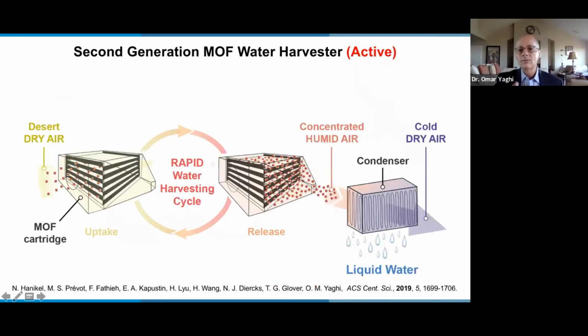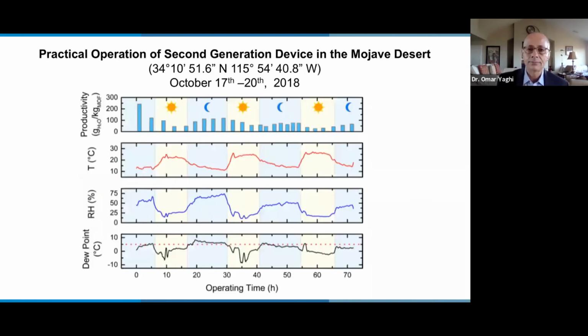So for this particular one, we designed what we call an active prototype, and it's based on MOF cartridges that are placed in the device in such a way that when some cartridges are collecting water, the other ones are releasing the water. So this one is active, meaning that we wanted to do more than one cycle a day. And so we use a solar panel to provide power for a fan that pushes air into the MOF and allows you to also heat the MOF so that you can control the uptake and release of water. Again, for a 1 kilogram device, we went to the Mojave Desert and showed that in fact it works in one of the driest deserts in North America.